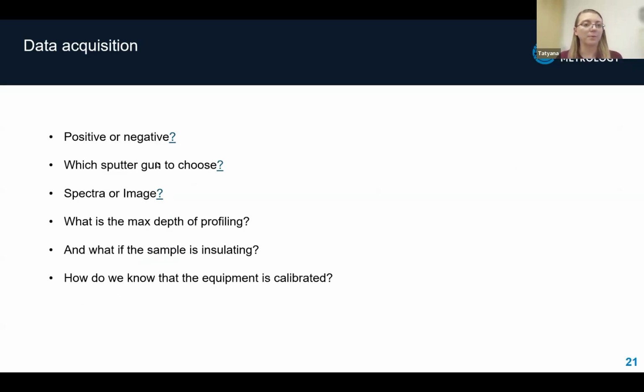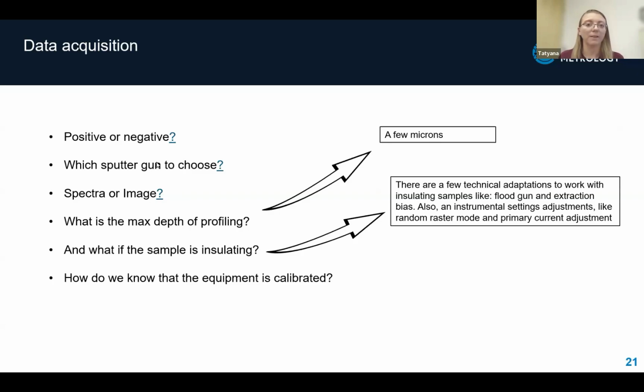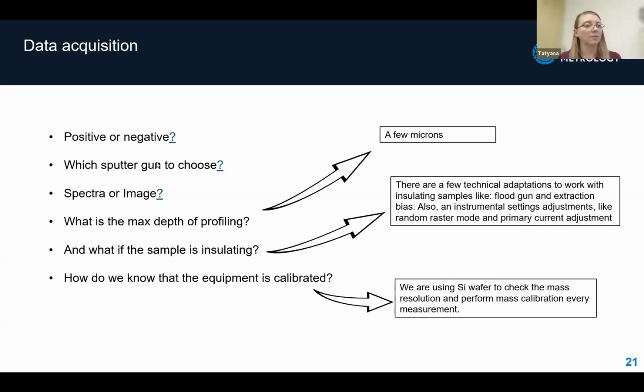What is the max depth profile? It's a few microns. And what if the sample is insulating? There are a few technical adaptations to work with insulating samples, like flood gun and extraction bias. Also, instrumental settings adjustments like random raster mode and primary current adjustment. How do we know that the equipment is calibrated? We are using a silicon wafer to check the mass resolution and perform mass calibration every measurement.